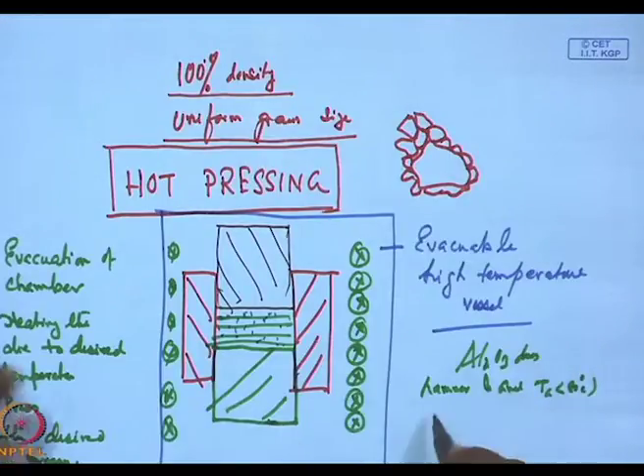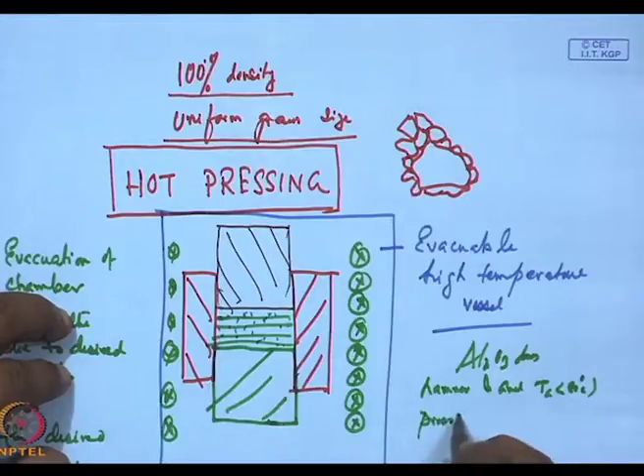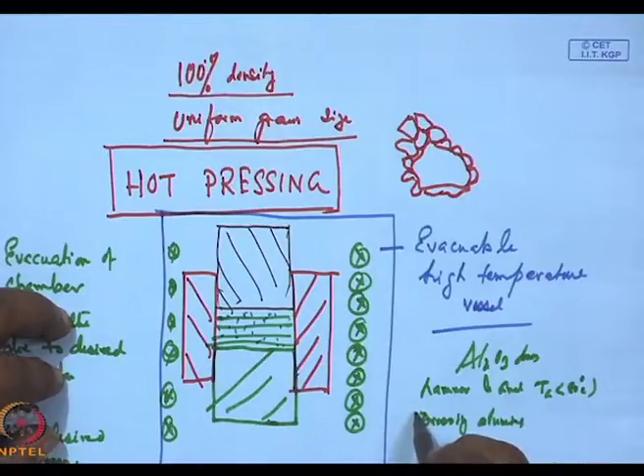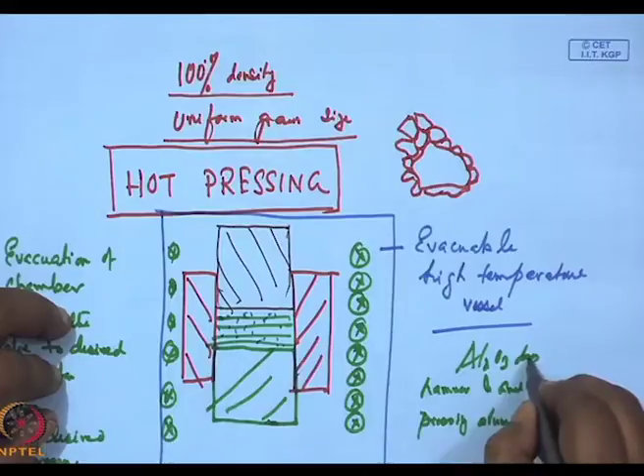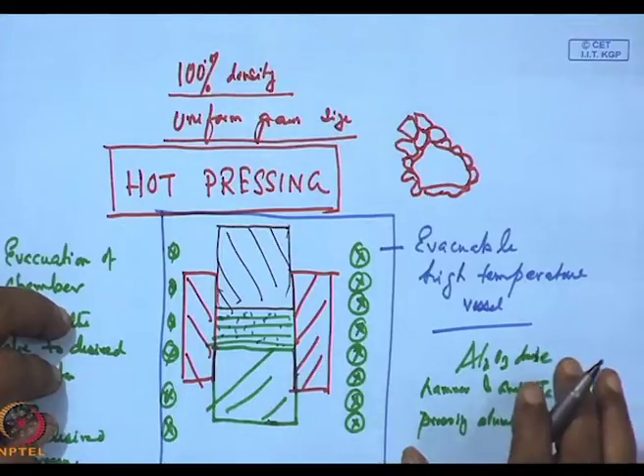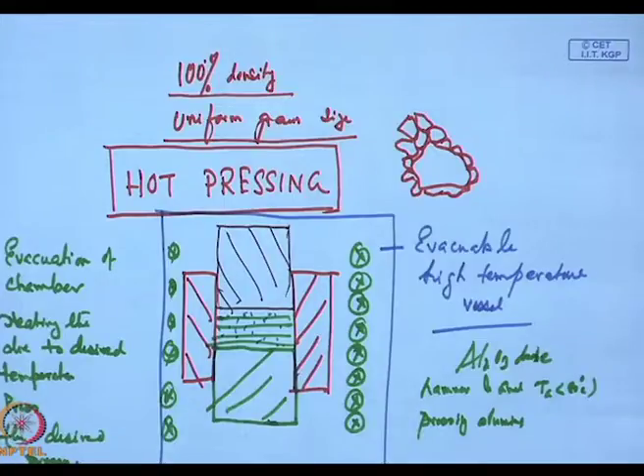So, if I am pressing alumina, it is better to use an aluminum oxide die as a complete set, because there the thermal expansion mismatch question does not occur. But in most of the metals, we will have die wall powder reaction which has to be cleaned out. Secondly, what we will have is this differential thermal expansion of the pellet and the die wall.